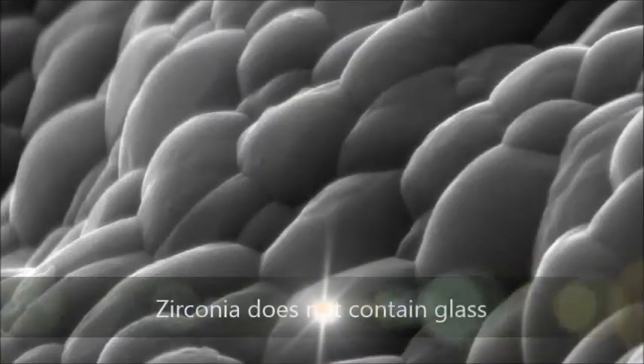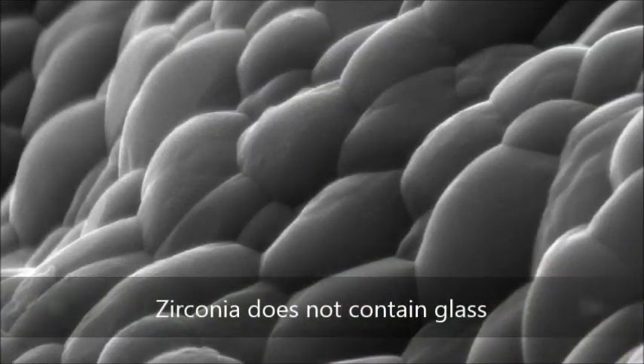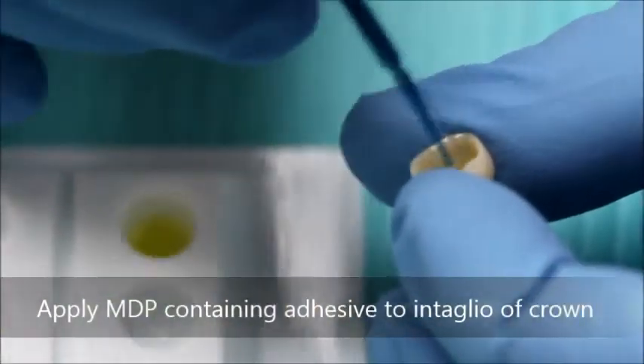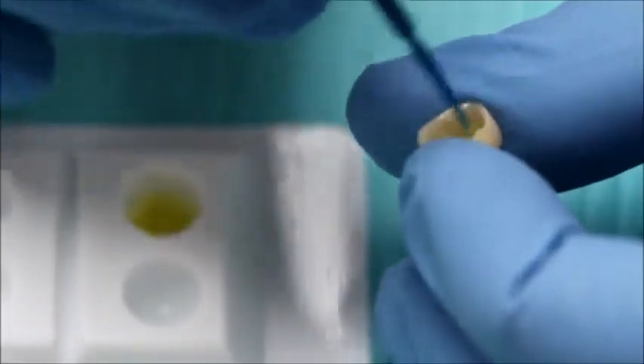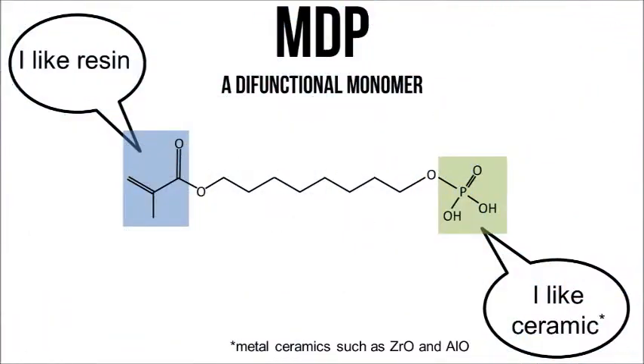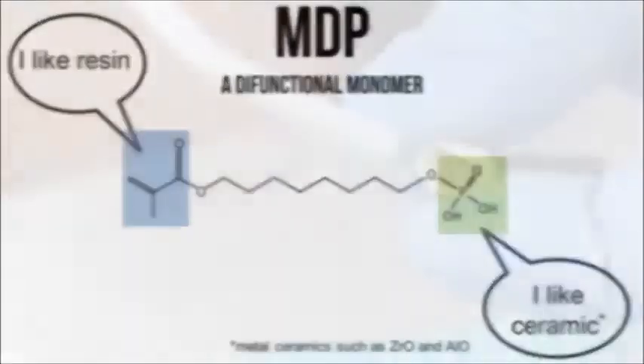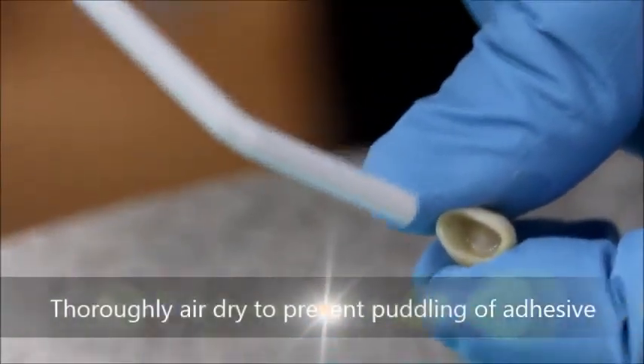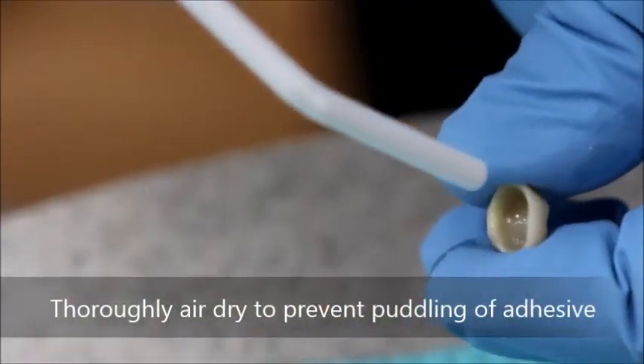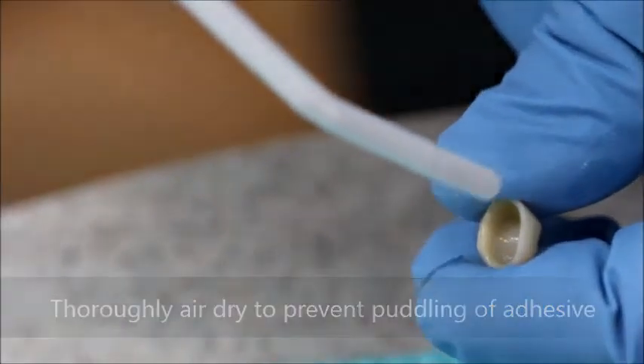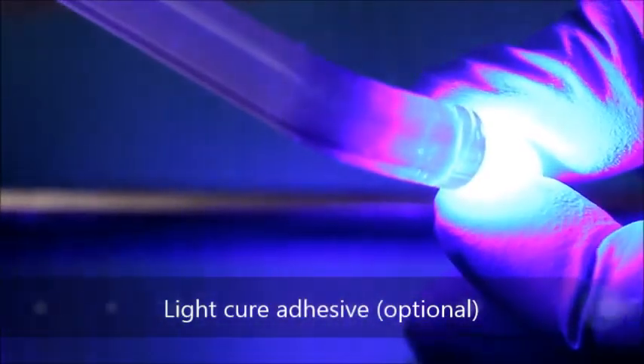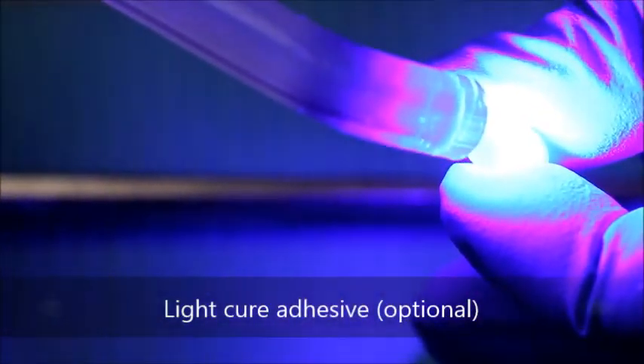Zirconia is a crystalline structure without glass, therefore it cannot be etched. In order to obtain a chemical bond between the zirconia and the resin cement, Scotch-Bond Universal is applied to the intaglio surface of the crown. Scotch-Bond Universal contains a molecule called MDP, which bonds to the zirconia of the crown and the resin of the cement. The inside of the crown is then thoroughly air-dried to prevent puddling of the adhesive, which may prevent complete seating of the crown. The inside surface of the crown can then be light cured to achieve optimal bond strength. Light curing, however, is optional.